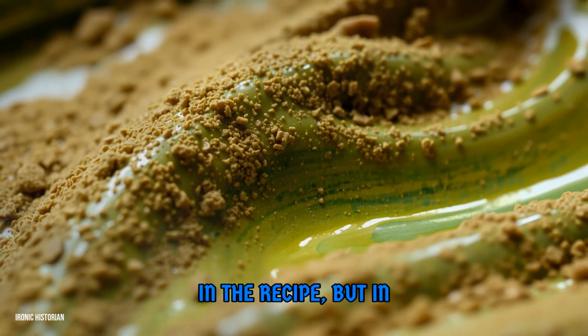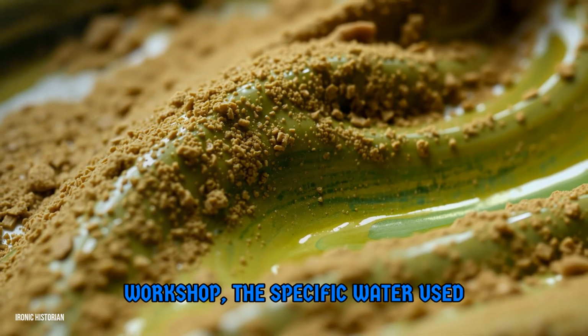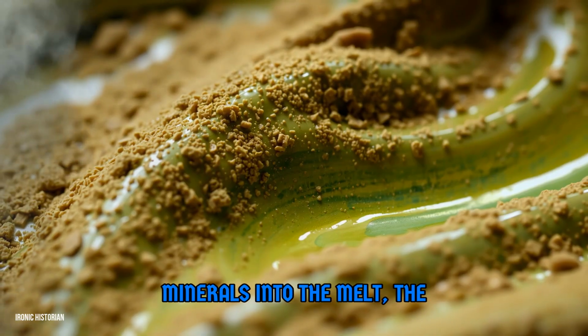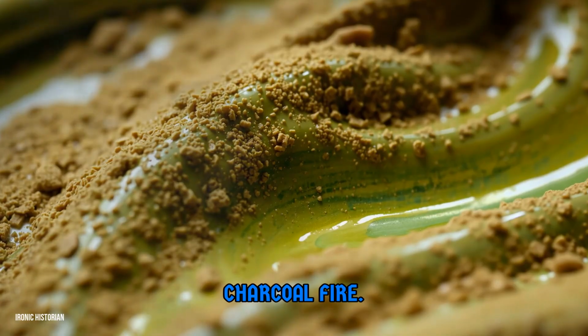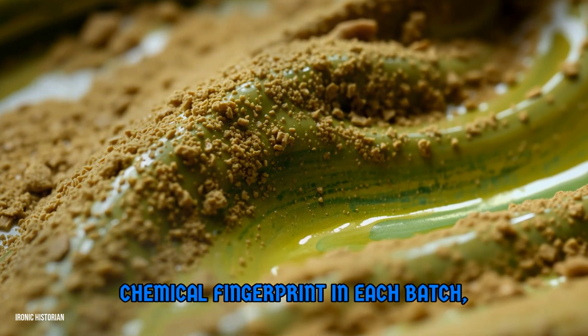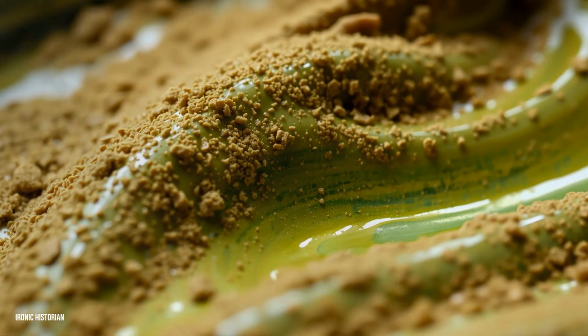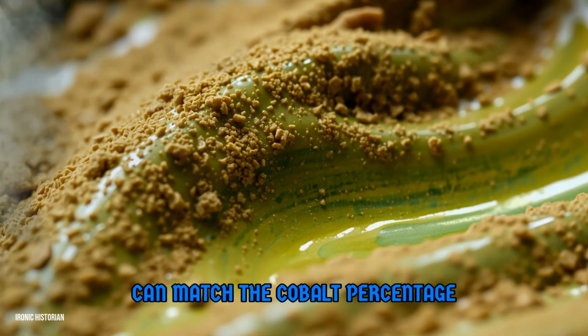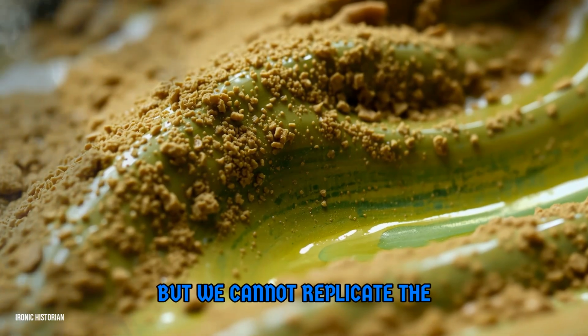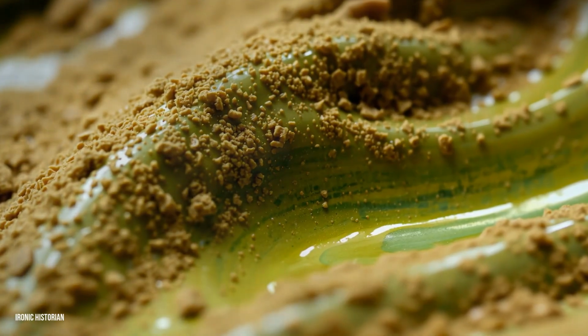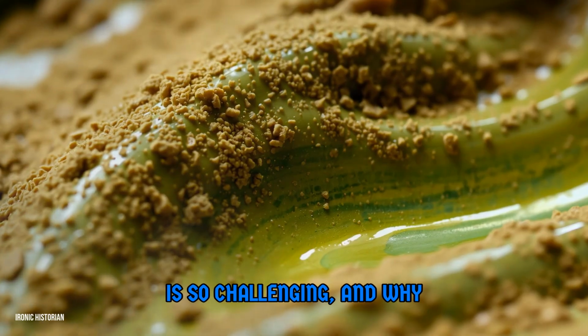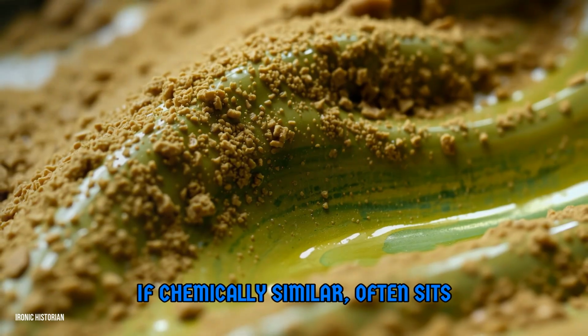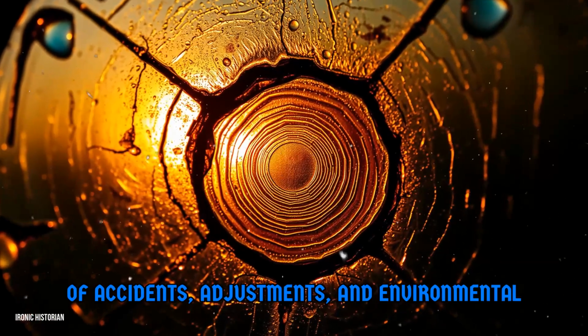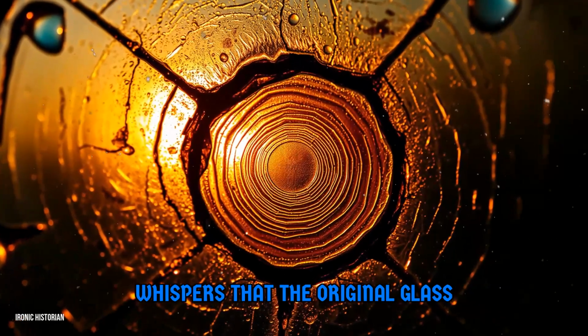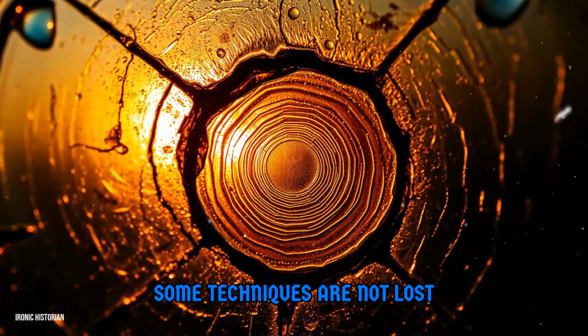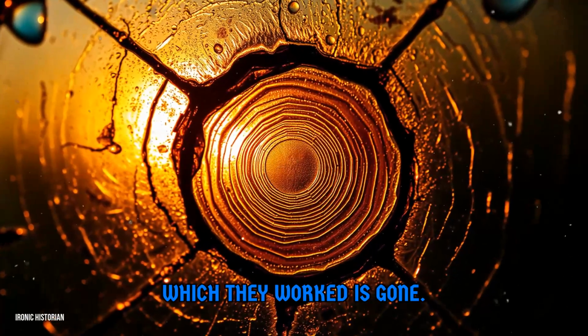The secret was not just in the recipe, but in the entire ecosystem of the workshop, the specific water used to quench tools, the clay of the crucibles that leached minerals into the melt, the constant, variable breath of a charcoal fire. These conditions created a unique chemical fingerprint in each batch, a signature of time and place. When we try to recreate a medieval blue today, we can match the cobalt percentage exactly. But we cannot replicate the 100 other variables that the master intuitively balanced. This is why authentic restoration is so challenging, and why a newly made piece, even if chemically similar, often sits differently in the light. It lacks the silent chorus of accidents, adjustments, and environmental whispers that the original glass absorbed during its creation. Some techniques are not lost because the instructions are gone, but because the world in which they worked is gone.